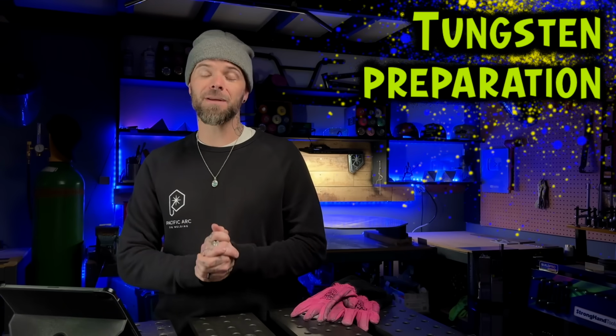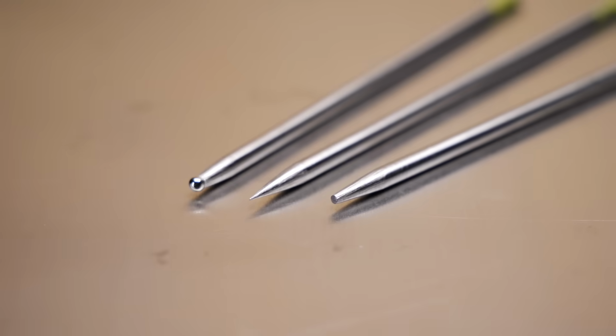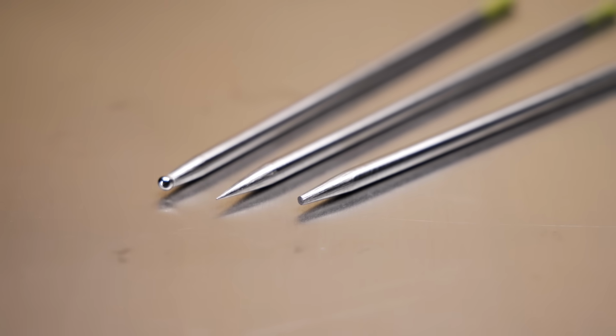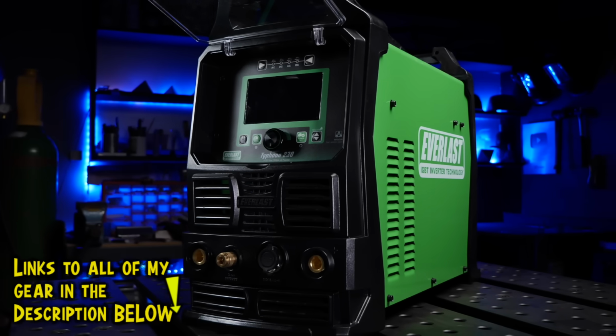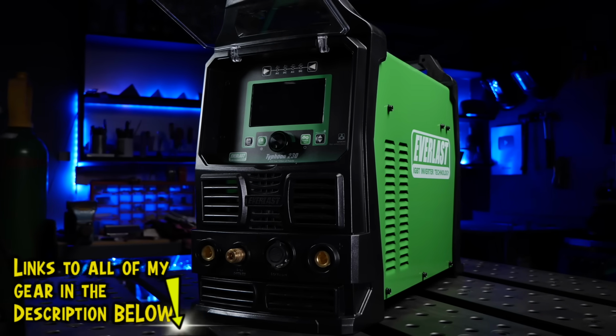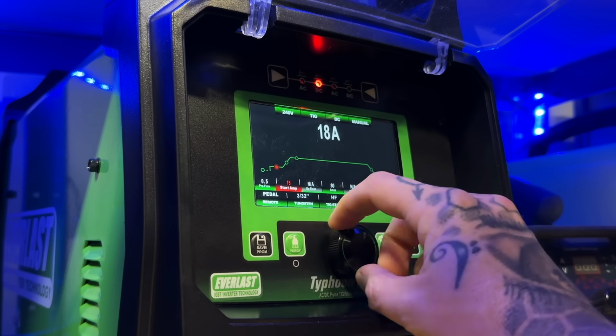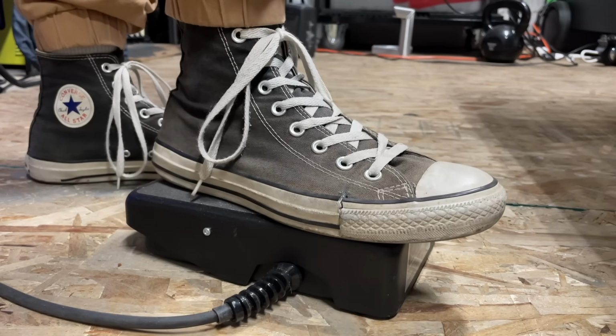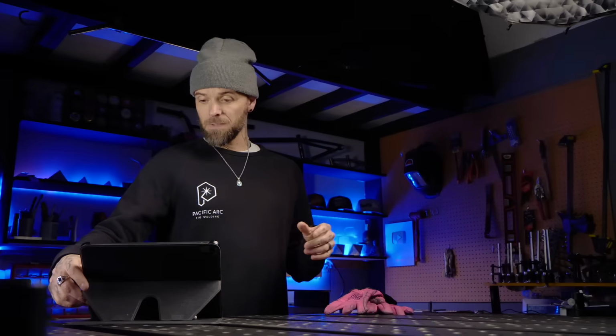control of your arc is absolutely going to be the tungsten preparation. All right, this is our little buddy here. This is the tungsten electrode. Now, typically when I'm getting my machine set up, I wanna program my machine with the lowest start amps possible. You can see me setting up my Everlast here. I have things set up to a pretty low setting that I can start with. This will be my minimum amperage on the foot pedal. And then once I get the puddle established, I can get into the heat a little more with my foot pedal.